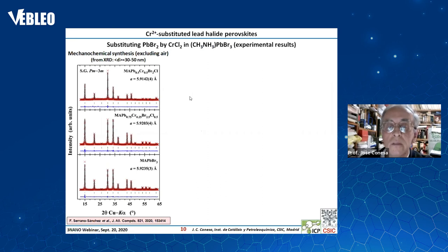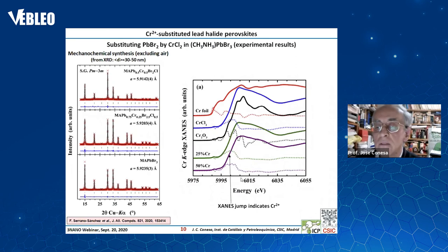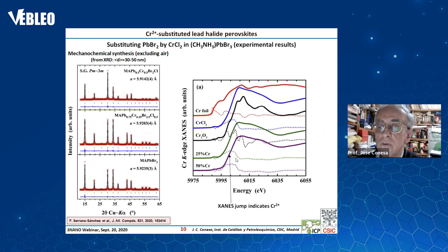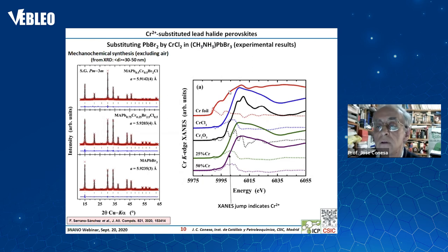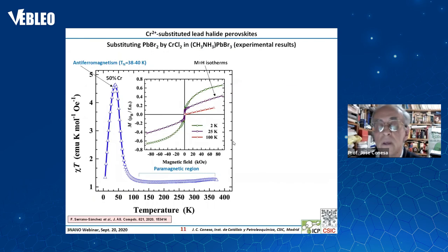We have been studying the valence state of chromium using XANES, a technique based on synchrotron radiation. We have been able to see that the position of the XANES edge jump is consistent with chromium 2+ and not chromium 3+. The position matches that of a chromium dichloride reference, not the chromium foil.